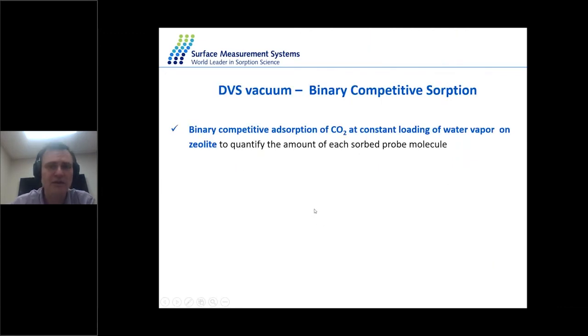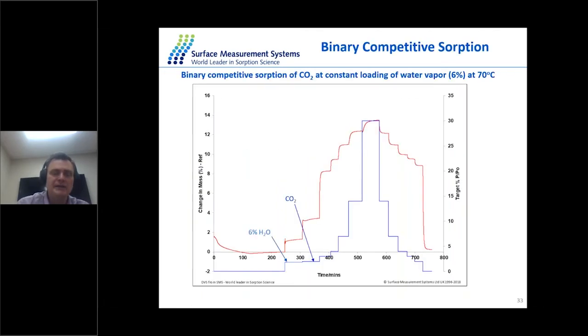Lastly, there's the binary competitive adsorption. In this case, you look at the pre-loaded material with water vapor, and then we introduce a second species on top of it. This allows us to quantify the amount of each adsorbate. So here we look at another material, one of the zeolites. First we outgas the material, then we introduce 6% of water at 70 degrees, and we wait for the mass equilibrium. So you get mass equilibrium. Then we introduce the pressure.